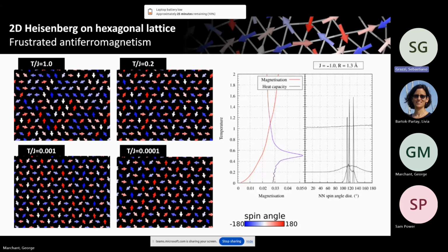And these peaks here correspond with this structure, and it does look fairly regular, but if you follow these lines here, you'll notice that the spins are very slowly rotating along these lines, and you can pick out the same behavior going along other hexagonal axes as well. This is demonstrating what nested sampling can do, which is that it can ultimately find this state, and also give us a temperature profile of what the correlations look like.